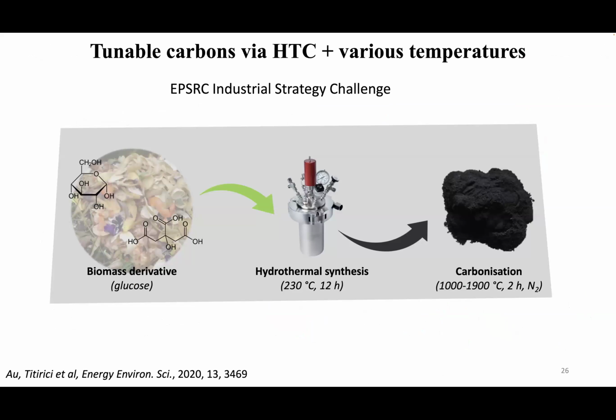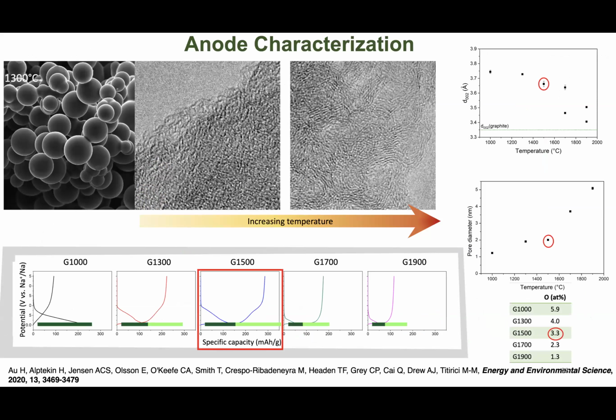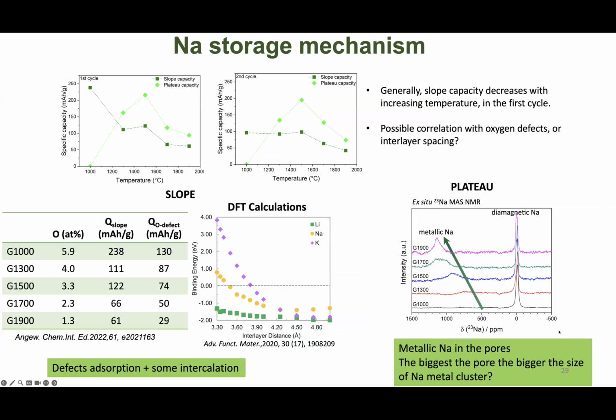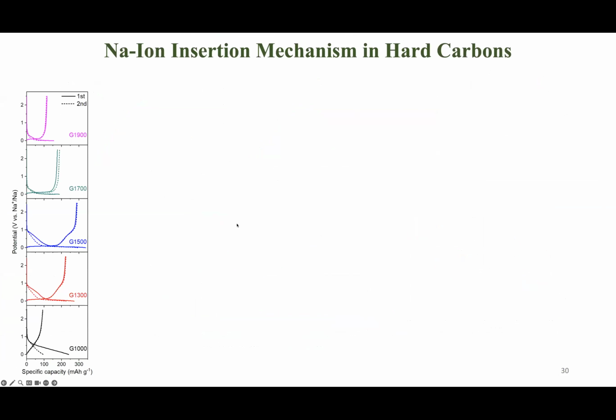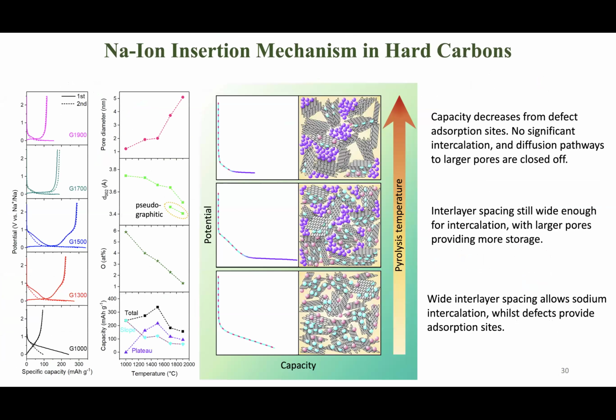So we've been doing these hard carbons from renewable resources using a mild hydrothermal synthesis for a while. And as I said, we've been testing this, and we've been doing this big study on the mechanism where we've looked at the effect of interlayer spacing, pore diameter, size. We've been using a lot of in operando characterization, such as NMR to figure out the plateau, but also DFT calculation to figure out the pores.